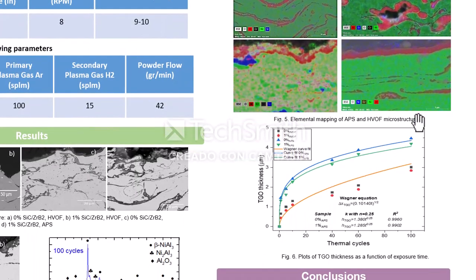Finally, the oxidation kinetics of the coatings were studied by plotting the TGO thickness as a function of time and comparing the results with two different equations: the Wagner equation and a sub-parabolic one. The graphs show the coating fabricated with HVOF displaying the lower oxidation rate and APS following a sub-parabolic curve. But more important, the samples with the addition of silicon carbide, in both projection systems, show the lowest oxidation rate.